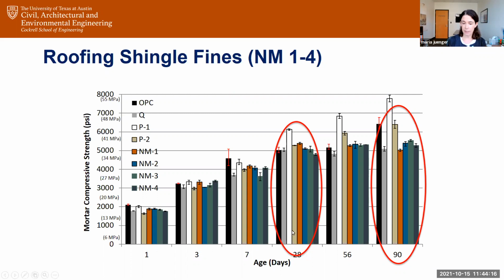If you start looking at the 28-day strength of, in this case, a mortar made with those materials, this black one here is the Portland cement. These materials, NM1, 2, 3, and 4, are the byproduct asphalt shingle aggregates ground very fine, in the same particle size as Portland cement. The P1 and P2 here are actually our pumices that we looked at earlier. So if you look at the 28-day strength, they look great. You think, oh, we've got a really great source of supplementary cementitious materials as a byproduct of these industries. It seems to not affect 28-day strength at all.